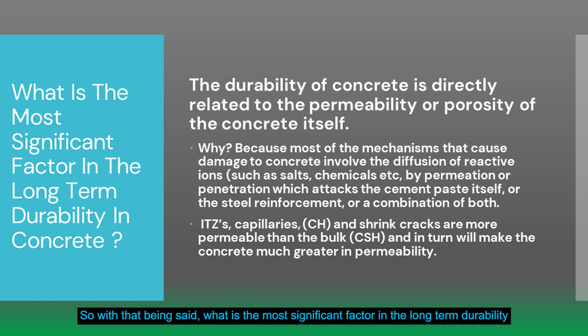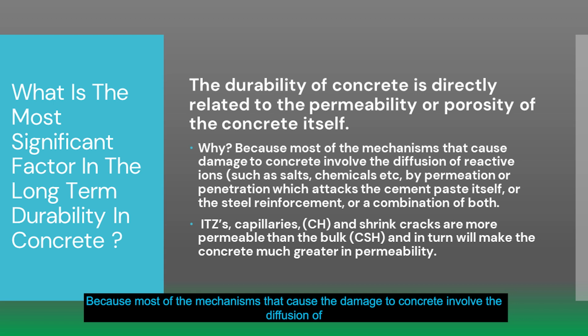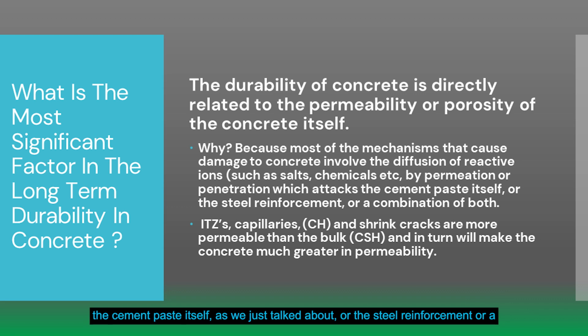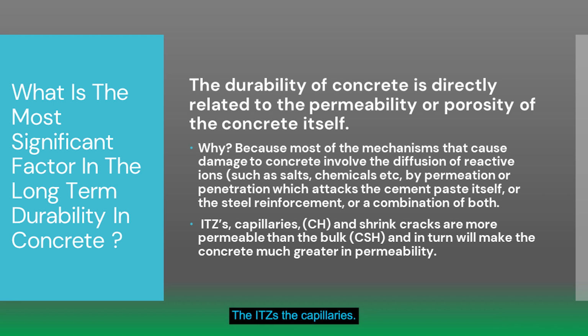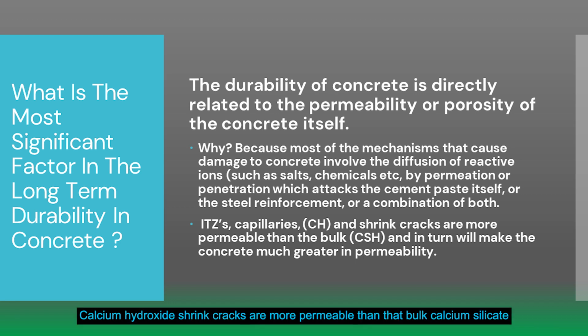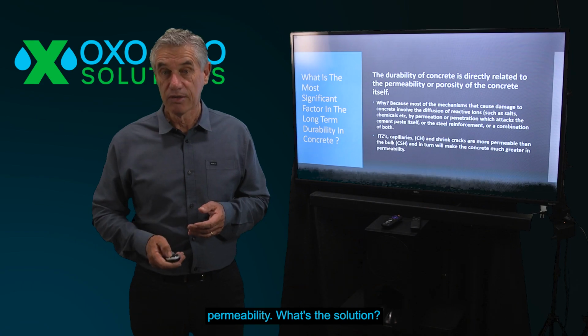So with that being said, what is the most significant factor in the long-term durability of concrete? Well, the durability of concrete is directly related to the permeability or the porosity of the concrete itself, as we were just talking about. Why? Because most of the mechanisms that cause damage to concrete involve the diffusion of reactive ions, such as salts and chemicals, by permeation or penetration, which attacks the cement paste itself, as we just talked about, or the steel reinforcement, or a combination of both. The ITZs, the capillaries, calcium hydroxide, and shrink cracks are more permeable than the bulk calcium silicate hydrate, as we just saw, and in turn will make the concrete much greater in permeability.